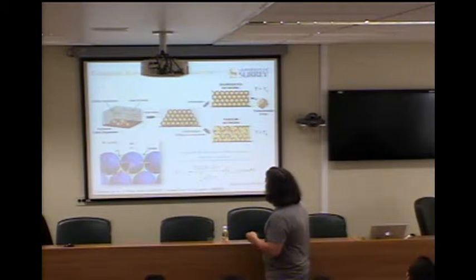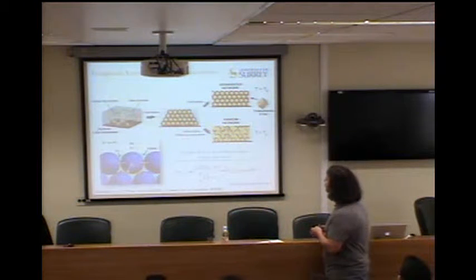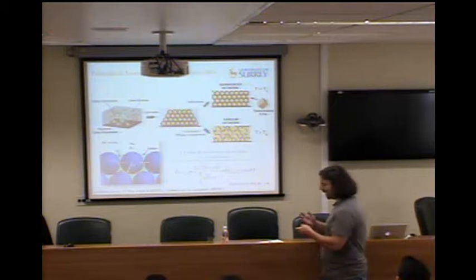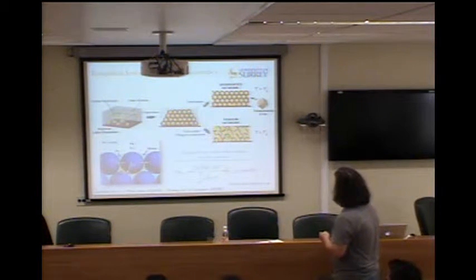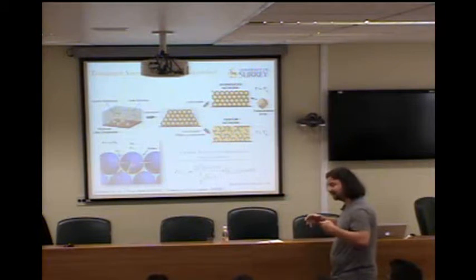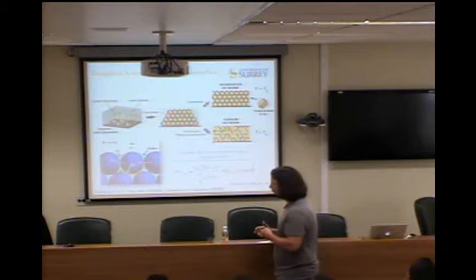So what happens when we add carbon nanotubes? Well, we add them in the dispersion. When the system dries, the idea is that the polymer particles come together, and they force the nanotubes to assemble at the interstitial points. Depending on how soft or hard the polymer is, if the polymer is hard, so it doesn't form a film, you end up hopefully with a segregated structure, like a bee honeycomb. If it's very soft, then the carbon nanotubes or the other nanoparticles can diffuse into the polymer structure, and you end up with some kind of random network. I won't go into the physics, but you can understand this in terms of the capillary forces during drying.